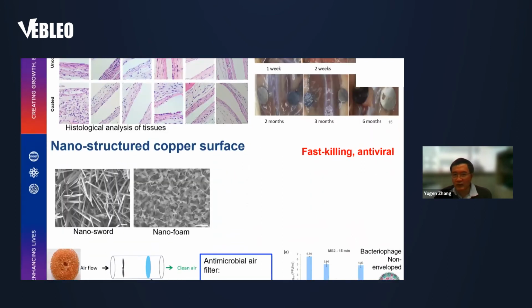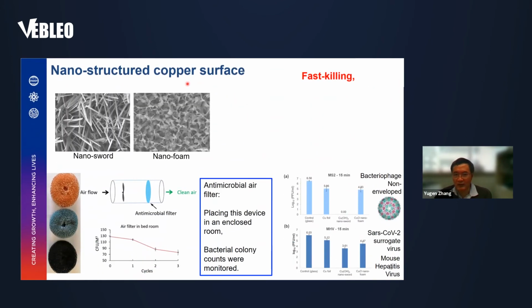And for the nanostructured surfaces, this is the last one. It's a copper surface. And we are looking for this fast killing and also antivirus properties. Because we know that virus size is much, much smaller than bacteria. So typically this kind of nanostructure cannot kill the virus. But here, when we developed this copper-based nano-sword or nano-foams, actually it demonstrates good antiviral properties.